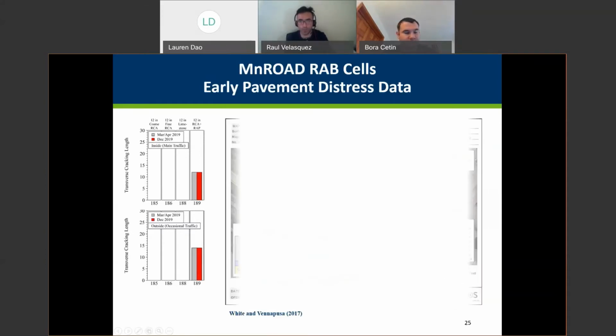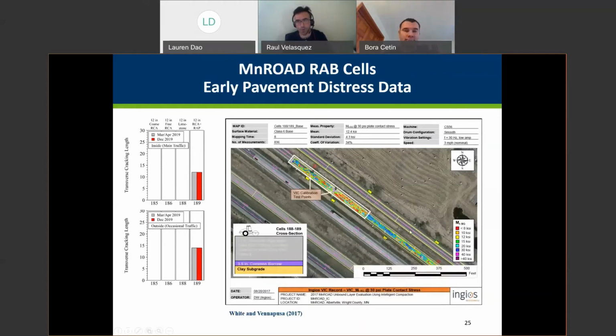Now, if I go into what was measured in the foundation, in the subgrade for cells 188 and 189, you see a lot more red spots, meaning weak spots, resilient modulus less than 8 KSI for the subgrade, and also a lot more variation, more red, orange, yellow, green, spatially spread on the subgrade for 189. That's interesting to observe because we know that thermal cracking is mostly driven by binder type, performance grade, aggregate type, and mix design, and there are some effects, but not significant effects from the foundation. So this is a quite interesting observation, and we have collected intelligent compaction data in other parts of our cells in Mineroad where we observe similar trends. So we're going to keep an eye on this interesting result.